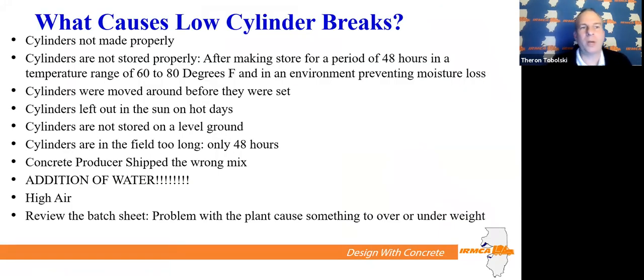What causes low cylinder breaks on jobs? Cylinders not made properly. Cylinders not stored properly, right? We talked about the first 48 hours, 60 to 80 degrees. Cylinders are moved around before they're set. Sometimes we see people cast cylinders, come back 4 hours later and then move them. But it's right in that phase where the concrete's starting to set in the cylinder, and they actually cause cracks by moving them. And then the cylinders break bad.